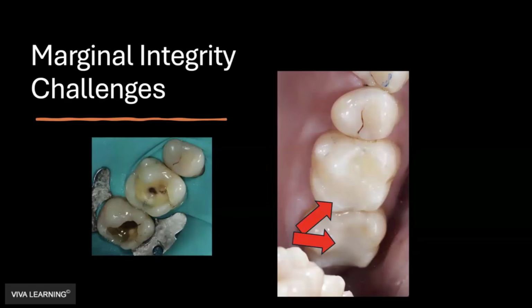So that line right there, basically what that's telling you is when I cured that composite, I did not place the layers properly enough, and that composite started debonding, pulling that enamel and kept creating little gaps right there. Even if you polish, even if you spend your whole morning here trying to polish that composite right there, these right here will be micro leakage. This will cause micro leakage over time.